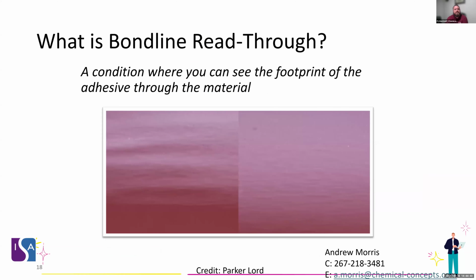Bond line read through. This is something that we see often in the sign industry, especially on thin gauge metals or ACM panels. This is where you can actually see the lines of adhesive through the material or through the finished product. This is caused by thermal expansion. It's basically the heat and the properties of that adhesive as it's curing. The temperatures that adhesive is getting to is causing an expansion and contraction of the materials that it's being applied to and causing that read through on the other side.